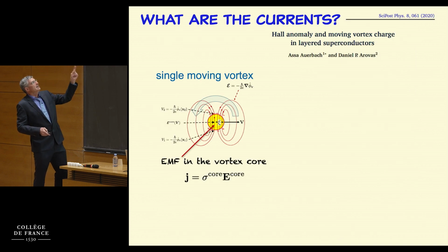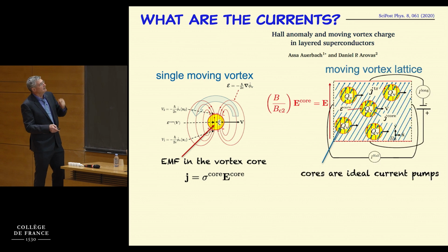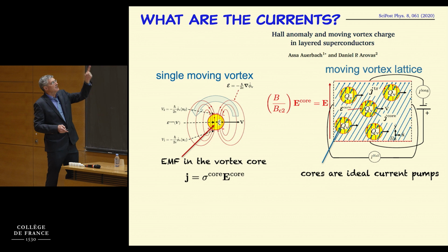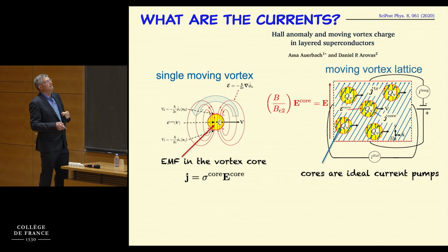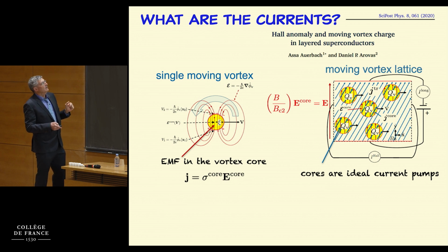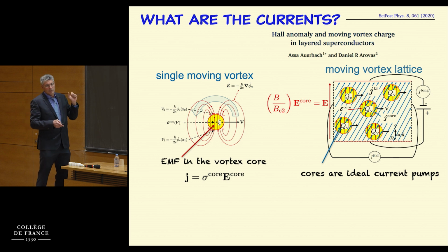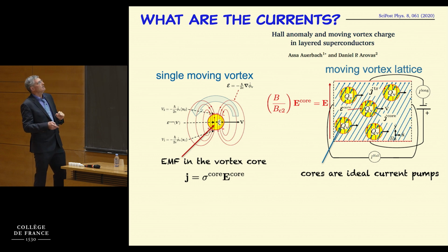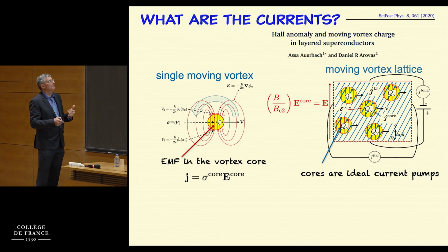So each vortex is creating an EMF, but all the vortices together are creating essentially the electric field that we said before has to be the same electric field that's measured outside. But inside the core, the electric field is stronger because there's a relation between the total electric field and the inside electric field coming from theory of polarization. But anyways, what we will assume as a model is that inside the core, which is size psi we said before, the transport is metallic, given by local conductivity, which is very close to the conductivity or extrapolated on the conductivity of the normal state.